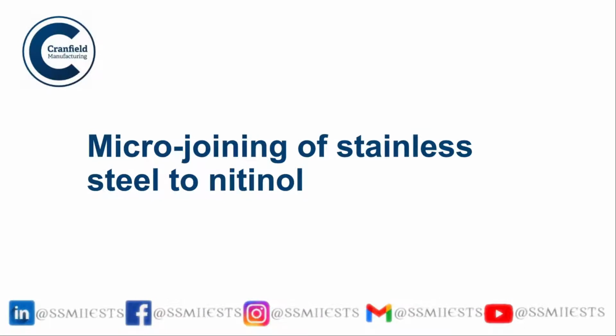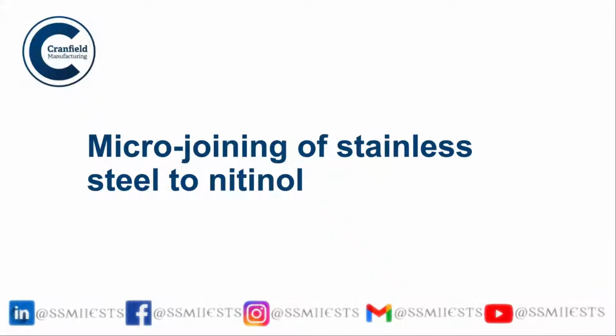Another example is microjoining. I will talk about joining of stainless steel to nitinol. Nitinol is a shape memory alloy. I'm not sure whether you are aware of nitinol. It has very good application in dentistry as well as in other medical applications, and often it needs to be joined to stainless steel. The problem here is serious, because stainless steel contains iron atoms and nitinol contains titanium atoms. Nitinol is basically 50 atomic percent nickel and titanium. Titanium and iron are a no-no situation. Not only can they not form a solid solution, but the intermetallics they form are absolutely brittle, and you cannot form a viable joint with iron and titanium.